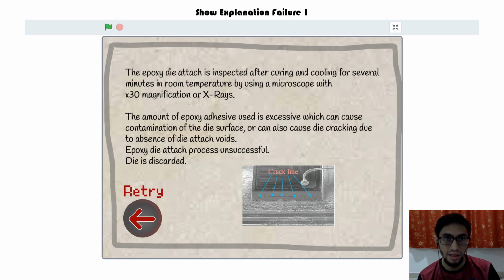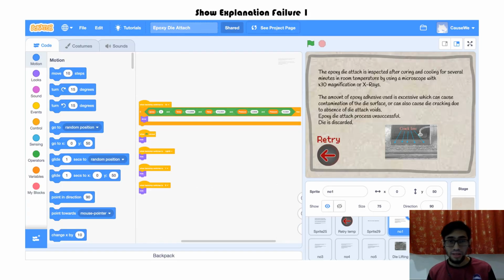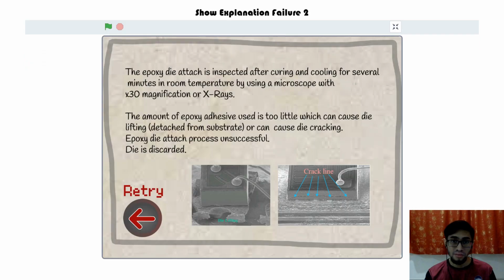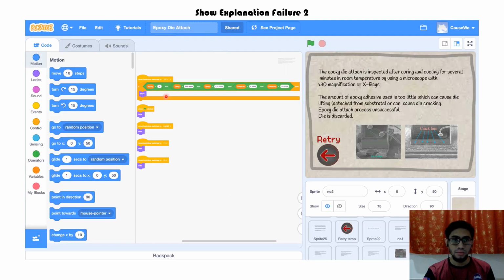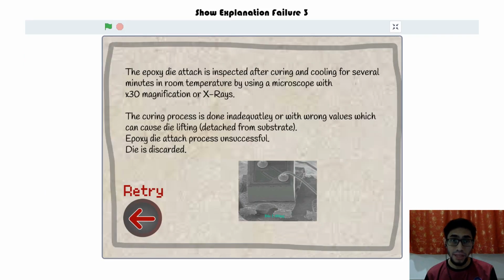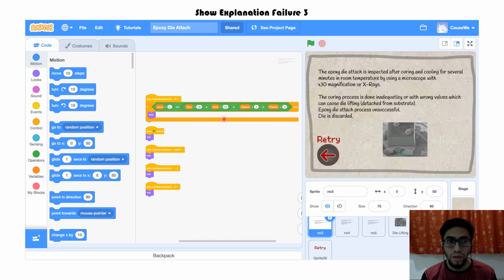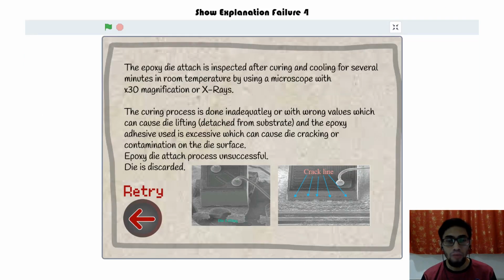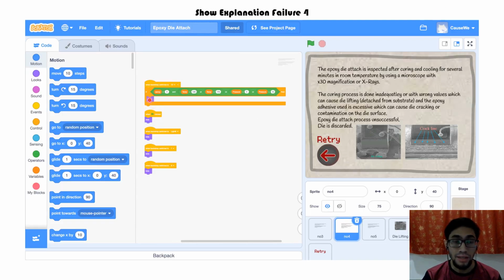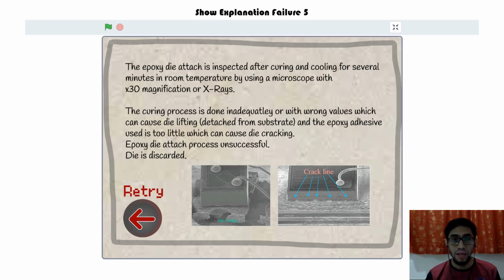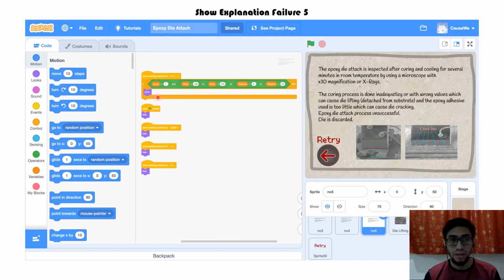Here is the failure type 1 page. The cause is excessive epoxy applied. Type 2 failure page. The cause is insufficient epoxy. Type 3 failure page. Caused by wrong curing condition. Failure type 4 page. Caused by excessive epoxy applied and also inadequate curing process. And finally, the type 5 failure page, which is caused by insufficient epoxy and also inadequate curing process.